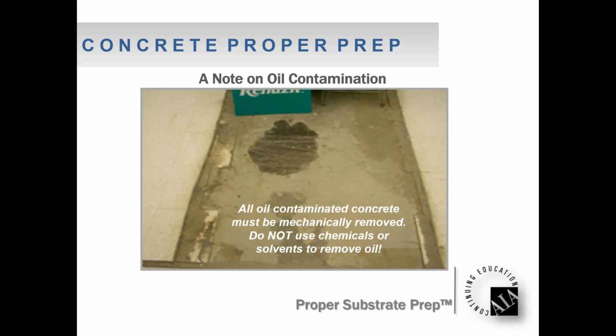Looks like clean concrete, but then all the oil that's penetrated the middle and the core of the slab wicks its way back up to the surface because you've opened up the surface again. So, if you know that there's oil contamination in the slab, sometimes it may require taking a core sample and looking at the cross sections. Most definitely, it may take prepping today and then evaluating the surface tomorrow to ensure that there isn't oil that migrates right back to the surface once preparation has been done.